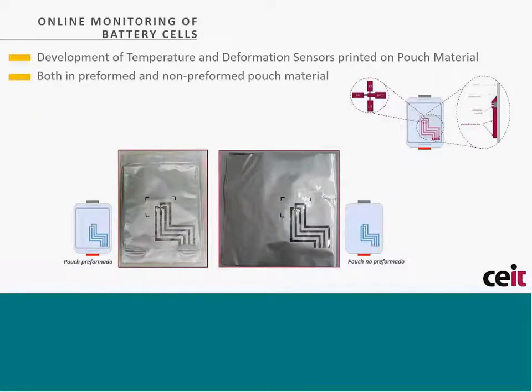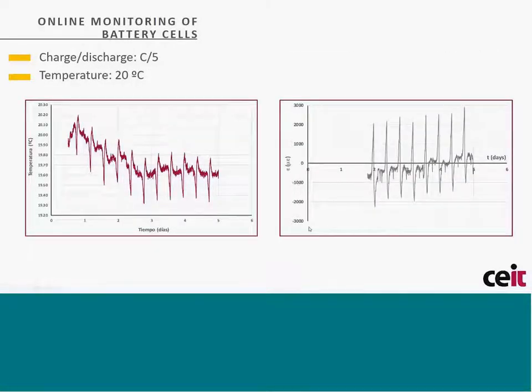So the different sensors have been printed not only in non-preform pouches, but also in preform pouches. You have here the sensor is this small part. You can see here on the right side of the slide. There is a sensing material with a specific geometry. And these big lines you can see here are the metallic connections in order to extract information from the sensors to the outside connectors. And well, we are quite happy with the results we have obtained for this.